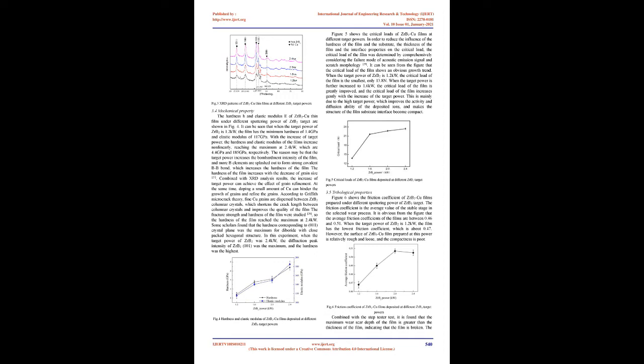When the target power increases from 1.2 kilowatts to 2.0 kilowatts, the diffraction peak intensity of Cu decreases and widens, indicating that the increase of ZrB2 target power will inhibit the crystallinity of Cu and refine the grain size to a certain extent. Zhou Kunli [26] believes that Zr and B, as refiners, have significant refining effect on Cu grains.